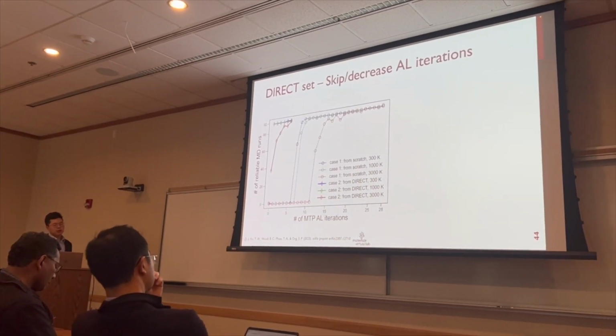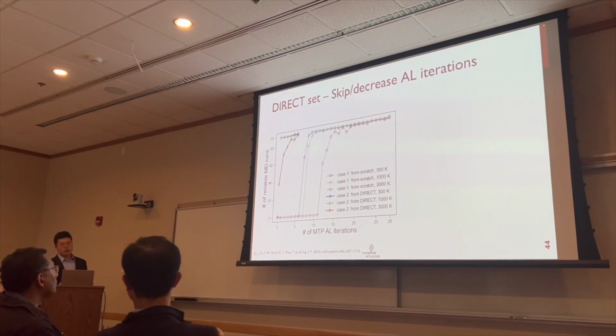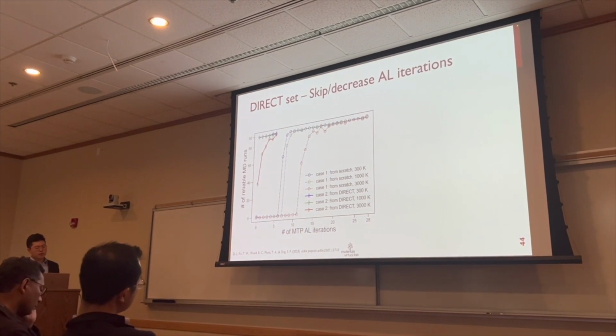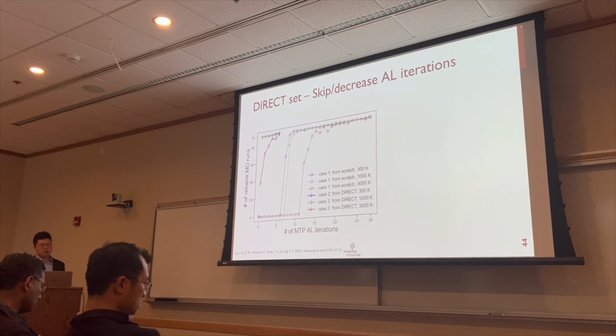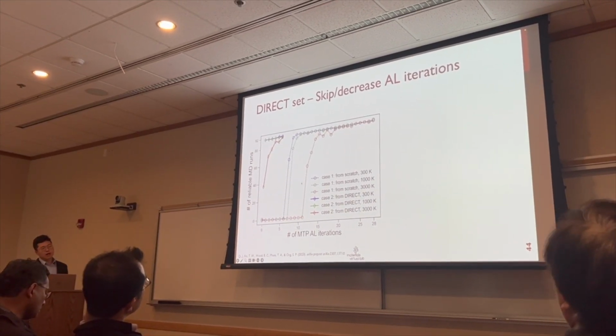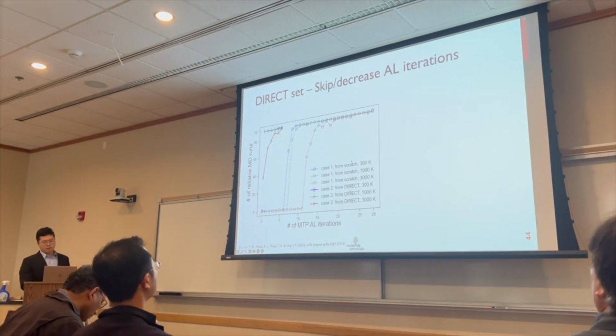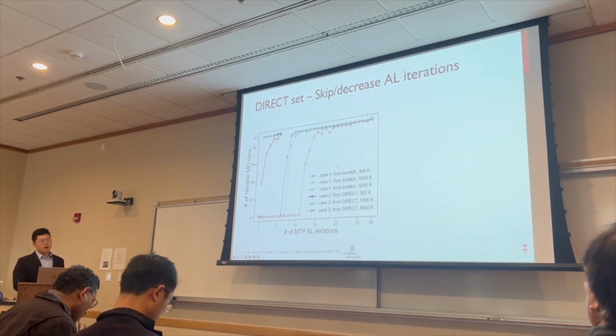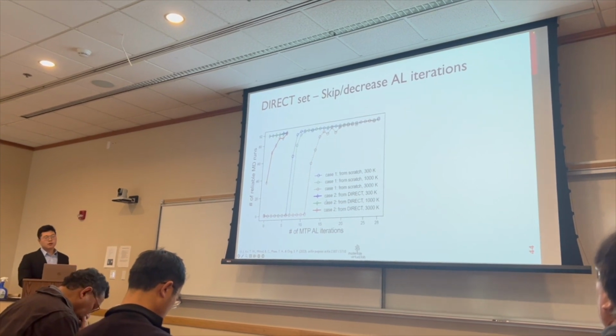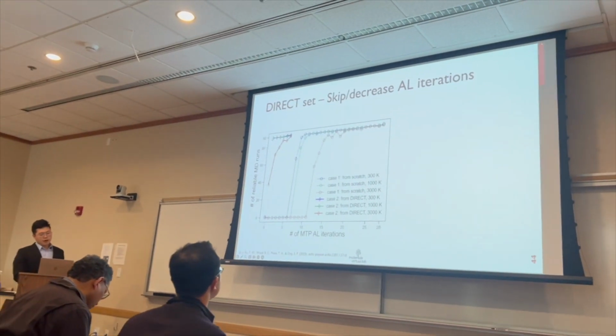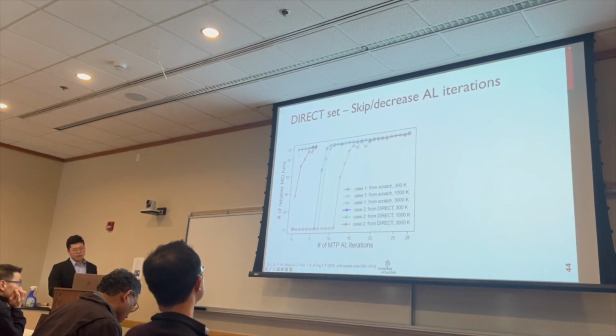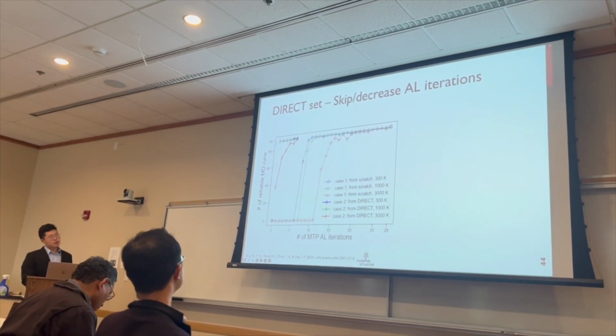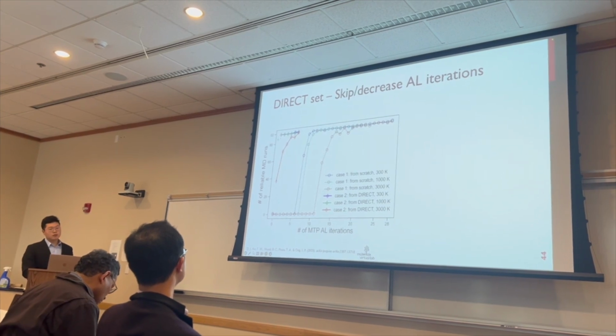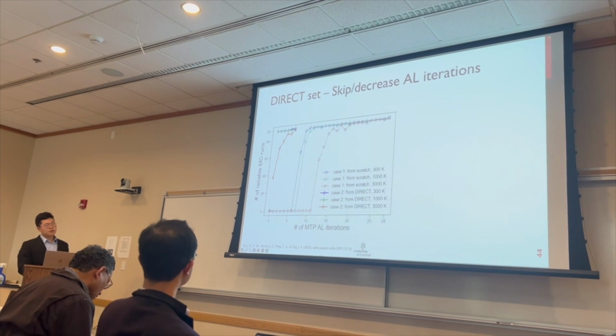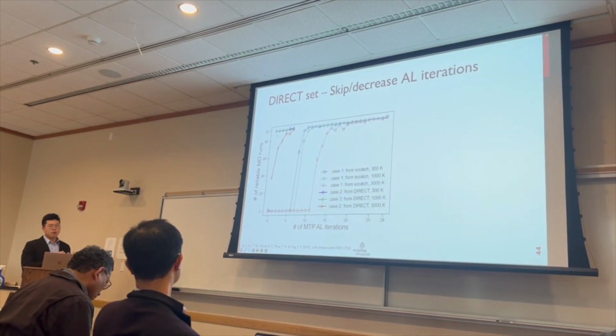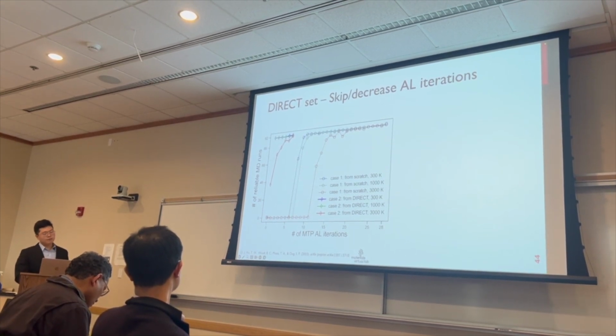Another interesting test we did is to see if our method can really achieve our initial goal, which is to skip or decrease the active learning iterations we need in the structure sampling process. Here I show you two scenarios of active learning training. Case one starts from scratch, which contains 91 initial structures of MD. The second case starts from the direct sampling dataset. If we start from the direct sampling dataset at temperatures of 300 and 1000 Kelvin, all the 91 MD simulations are already reliable without any active learning iteration. So this tells us that our direct sampling can serve as a very good sampling method to sample, in just one shot, the structures as training data for MTP without further active learning.